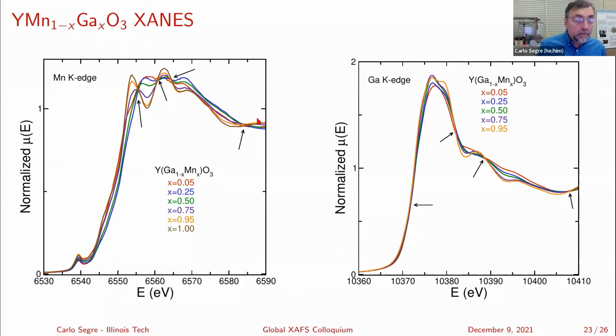However, in general, we're seeing the same kind of phenomenon. So we said, well, this is what we have, let's take measurements and see what we get out of the XANES. And in fact, the XANES still show isosbestic points, and that would indicate that we're having the same thing happen in this system. The gallium edge also shows isosbestic points.